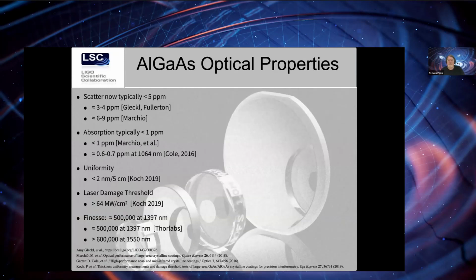Now, of course, coatings have to have good mechanical properties and good optical properties, but AlGaAs has excellent optical properties as well as excellent mechanical properties. So you can see that you get very low scatter, very low absorption, good uniformity, high laser damage threshold, and excellent finesse for these coatings.